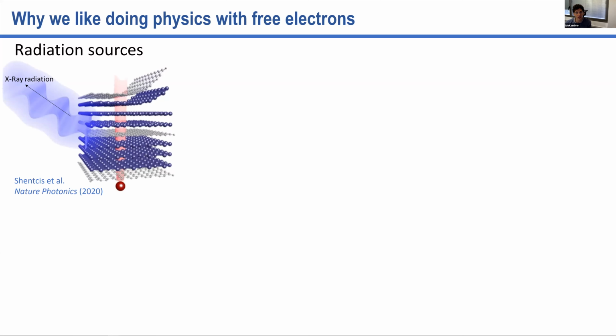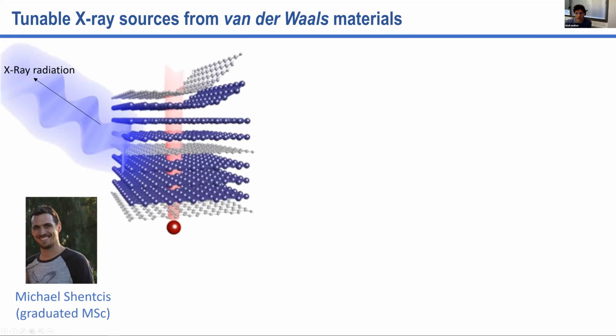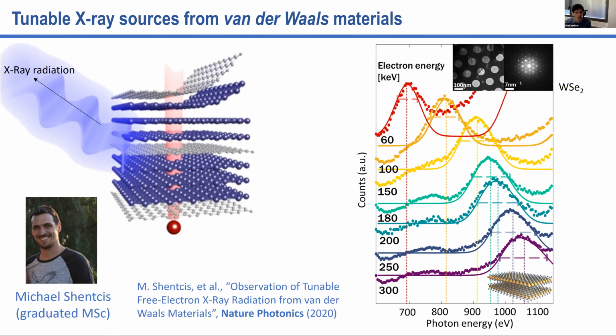where those van der Waals materials are interacting with the electron in a way that causes the electron to modulate the bound electrons in the material and create a set of dipoles. You can think about it like an antenna that is created along the trajectory of the electron, where different atoms along this antenna, different layers of the van der Waals materials, are modulated in a different way, so they all radiate in synchrony. And then the radiation we get, instead of being the typical material characterization that EDS gives us, is suddenly something that is created in a synchronized way by the electron driving them.